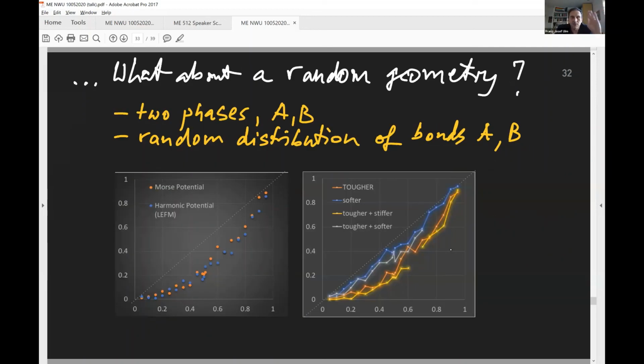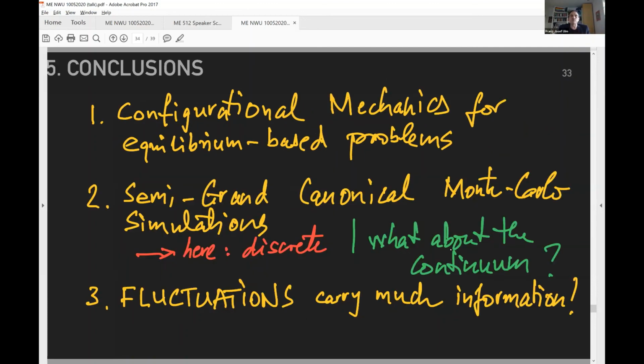Okay. Now, what about random geometry? A similar type of conclusion. Random geometry, I mean, I have two phases and I randomly attribute phase A or phase B in the system here. You have a similar type of situation. The tougher and stiffer one turns out here to be very similar to the softer material. But all I wanted to show you here in essence is how you can apply this semi-grand canonical fracture mechanics approach for homogenization of fracture properties with the same rigor as we deal with bounds in elasticity, diffusion, and other linear type problems. This brings me to my conclusions.